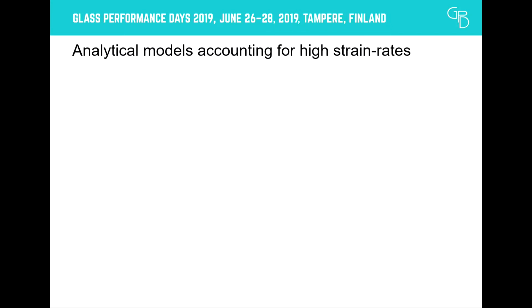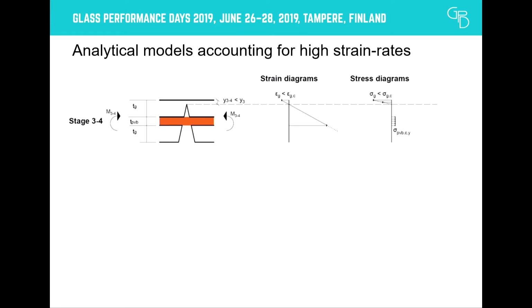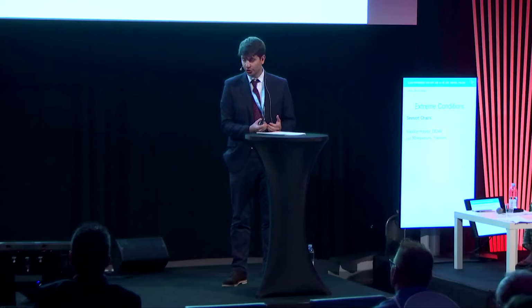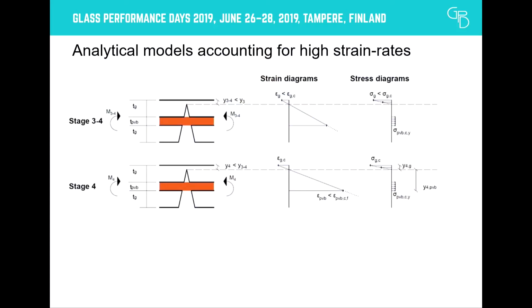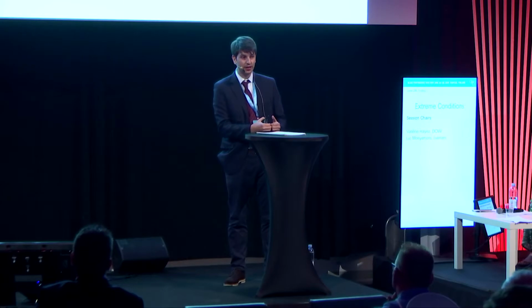Therefore, following the yielding of the interlayer, as more loading is applied to the structure, the strains will keep increasing. However, as the material law described is elastic, perfectly plastic, the stresses cannot exceed the yield value. At this stage, therefore, the plastic neutral axis will shift upwards to accommodate this change. Eventually, failure will occur when the attached glass fragments fail in compressive crushing. At this point, we can define the ultimate moment capacity by taking moment equilibrium about the plastic neutral axis. The curvature capacity at this stage can be defined by still assuming plane sections remain plane and a linear relationship for the strain diagram.